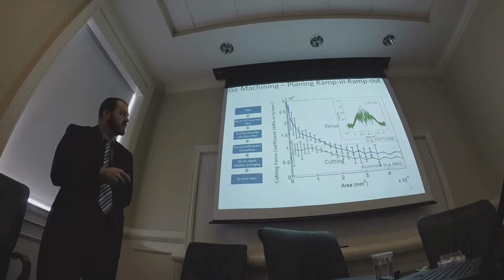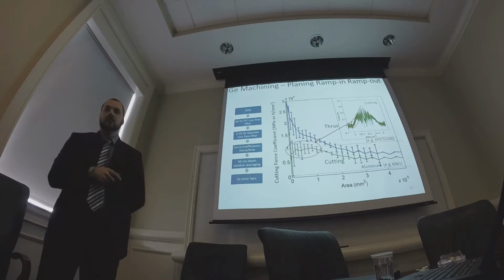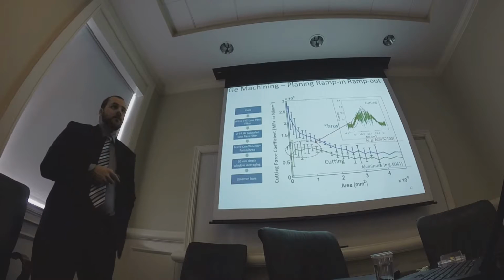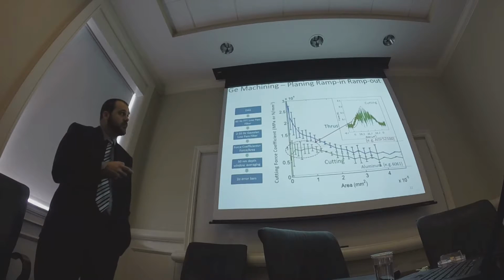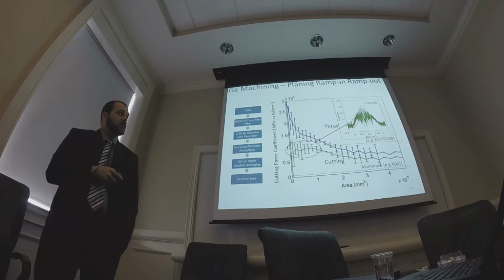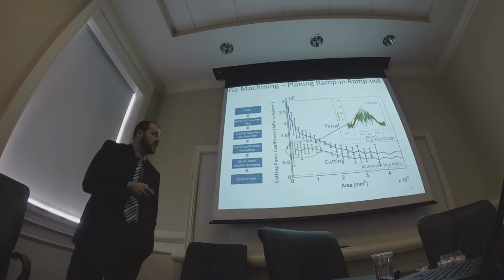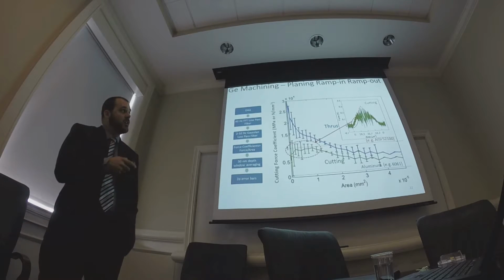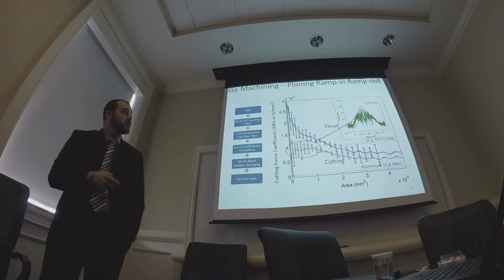So this region right here corresponds to that well-behaved region that we saw in the round nose cut, where we saw very, very little fracture here, but no fracture further down. So we've got a nice, relatively flat cutting force coefficient, and then our fluctuations start to increase.